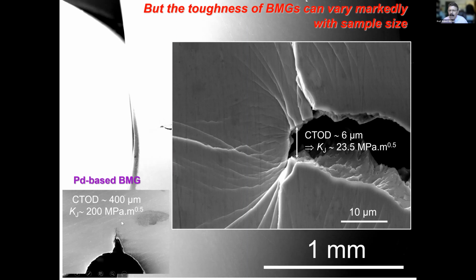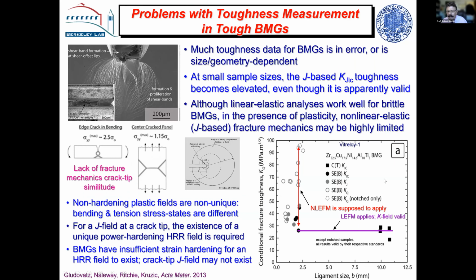Now, if you look at our data, this is a plot of the fracture toughness for a particular bulk metallic glass. We look at the fracture toughness versus the size of the sample. It's a ligament size. It's how much material you've got underneath the crack. Provided we have a big enough sample and linear elastic fracture mechanics applies, everything looks pretty good. But as soon as we get into the non-linear elastic fracture mechanics regime, the data is all over the map. And this is where we'd seen that 200 in the small sample and the 20 in the large sample. So we got this big change. So what's going on here?